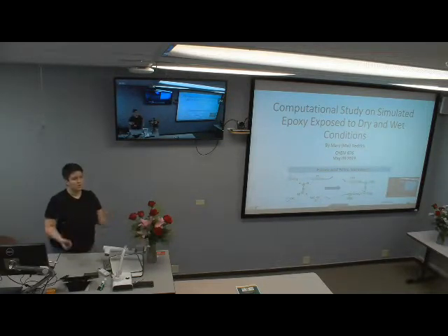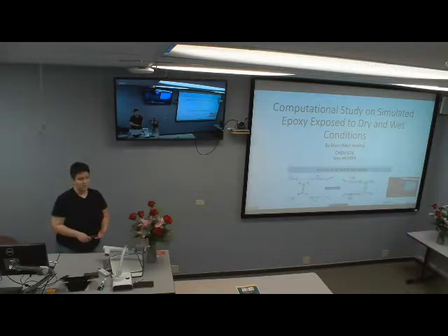So, in a polymeric material, if it's doing what it's supposed to, if you expose it to water, it could plasticize or those kinds of things. But my TG was going up, which was showing that my epoxy was becoming more brittle. So it was really hard because we didn't have a chance to do formulations or experience any of that because we have patents that you have to navigate by. But a way to go through this was a computational study, yes?